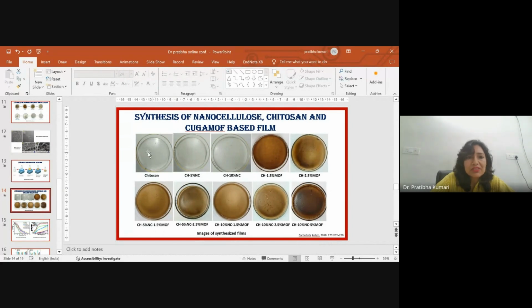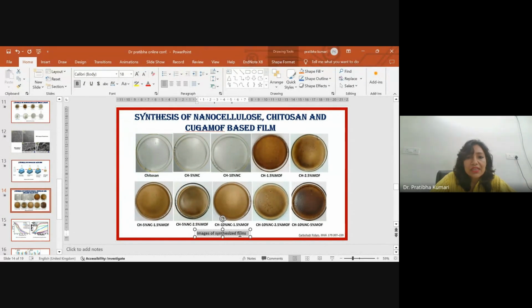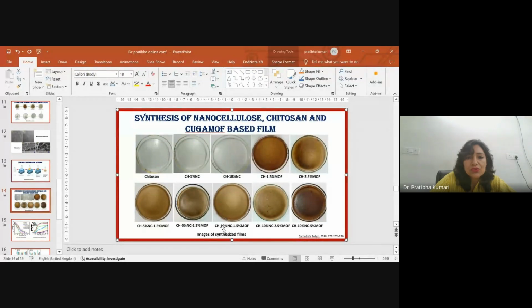Here you can see, this is the film of the chitosan. Nothing is added, just the chitosan film is there. Then we added 5% nanocellulose in the chitosan, we'll get this type of film. 10% nanocellulose, this is the film. Then we added MOF in it, 1.5% MOF is added, then 2.5% MOF is added. And in this film, you can see there is a combination of nanocellulose and the MOF. And then we increase the amount of the MOF. Then here we increase the amount of the nanocellulose to 10%. Then again, we increase the amount of the MOF from 1.5% to 2.5%.